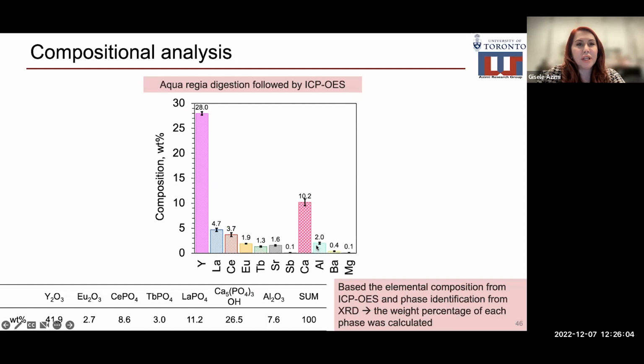We obtained the compositional analysis by digesting the sample in aqua regia, which is a strong acid, and measuring the concentrations with ICP-OES, inductively coupled plasma optical emission spectroscopy. We saw that this sample contains 28 weight% yttrium, 1.9 weight% europium, and 1.3 weight% terbium. Based on this chemical composition and XRD determined phases, we obtained this composition for the feed in terms of yttrium oxide, europium oxide, or the rare earth phosphates.